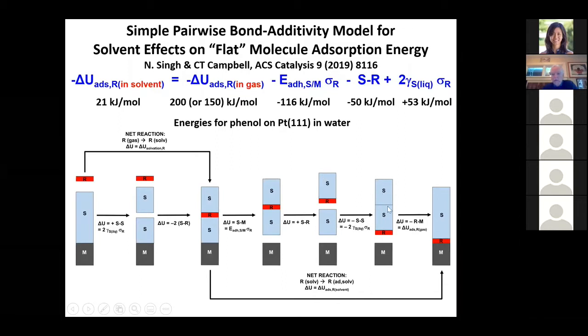And that's just making the solvent-solvent binding, which again, by definition, is just the surface energy of the liquid solvent times the area that you're doing that for, which is two faces that bind here, this face and this face. So we have a factor of 2. So that's downhill in energy. By that, we know that number. We know the surface energy of liquid water.